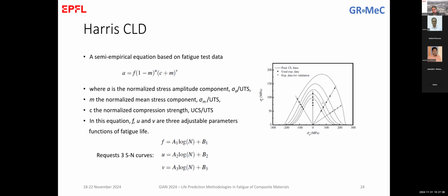This is a good approach, but we've seen with applications for different data that it has some problems. A very simple one, I can already explain: since this is only a mathematical equation, it doesn't take into account any physical mechanisms of the material. In some cases it gives this kind of behavior. It goes below, and this is not possible. It's like doing fatigue testing with a negative amplitude, which physically is not possible. Fatigue testing always has an amplitude which is a positive value. So it's the mathematical implementation of the model that gives some problems, but globally it is a good model. It has accurate results.